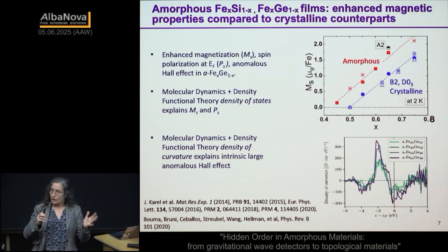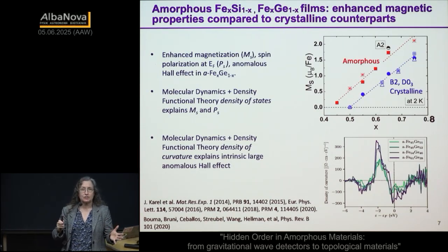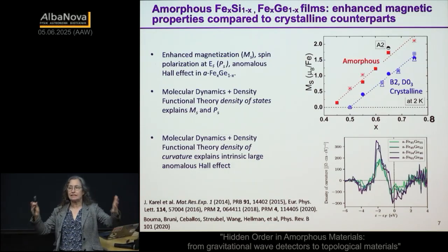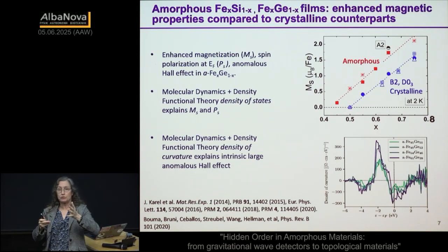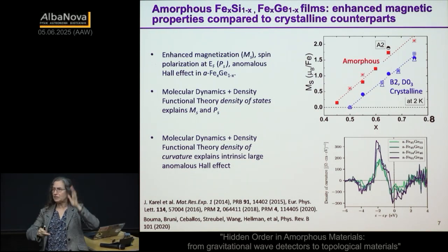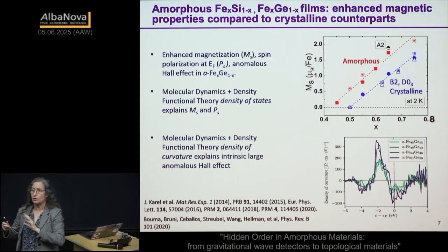You do it the way you do all amorphous materials in density functional theory: you make an enormous unit cell inside of which it's melted and then quenched, sort of like you would do in real life. Melted, quenched, you do it a bunch of different times so that you have a whole bunch of manifestations and you average over all of those.